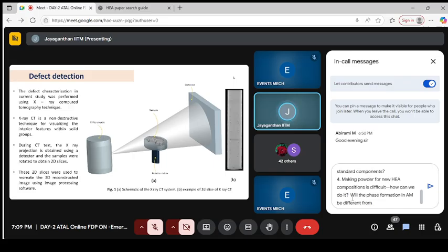And again, if you don't use appropriate laser energy density, you end up seeing either over melting or under melting. We talked about over melting: it may vaporize, and that may result in entrapment of gases. When I say defects in a 3D printed part, you can have mechanical pores due to gas entrapment, or even metallurgical pores, if you don't take care of proper process parameters for 3D printing.